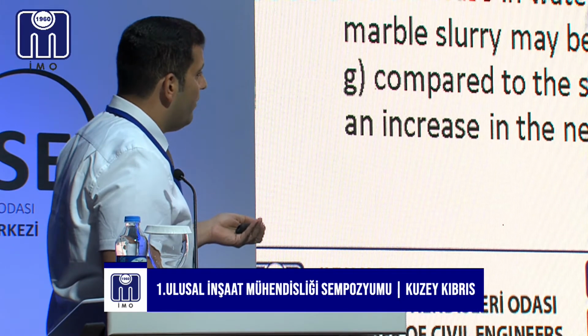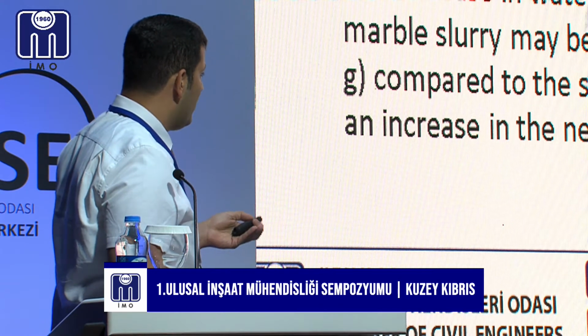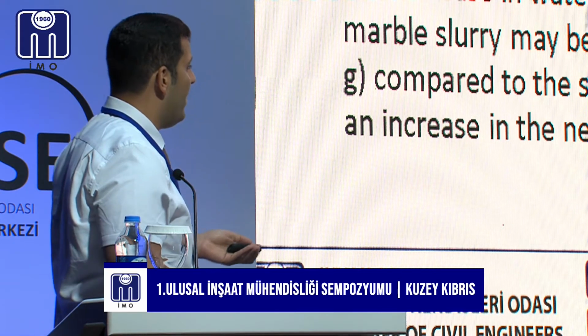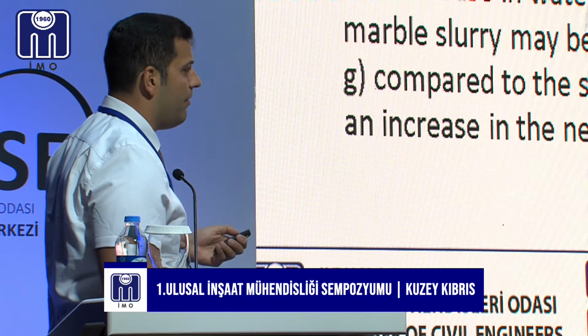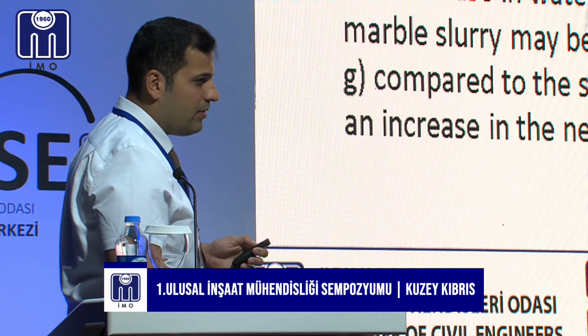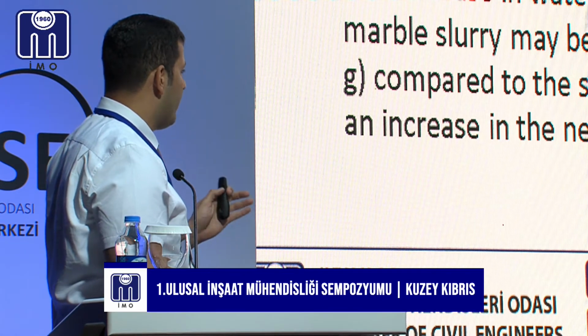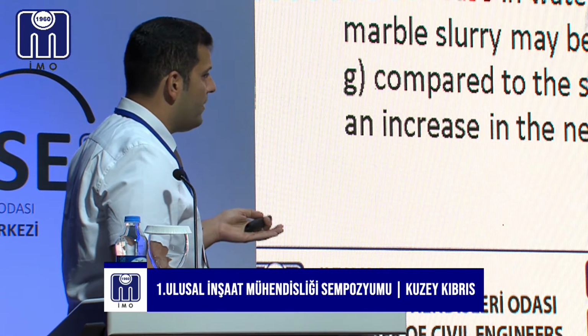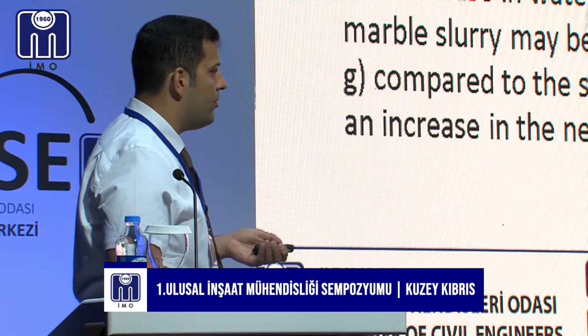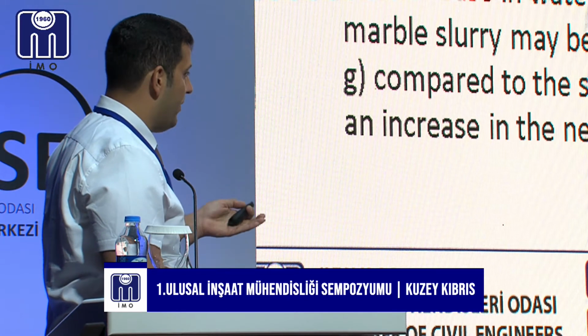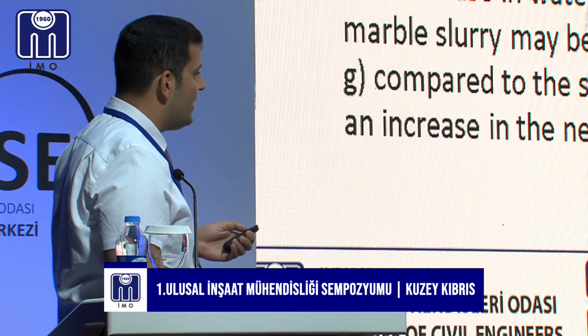The increase in water demand of cement composites containing marble slurry may be due to higher surface area, which is around 0.67 square meters per gram, compared to the surface area of the cement, which is 0.32 square meters per gram, which leads to an increase in the need for water.